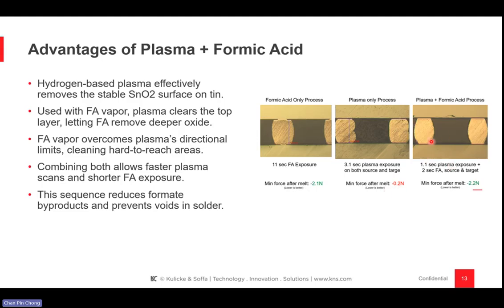And if you look at the combination of both plasma and formic acid process, it reduces from 3.1 seconds to 1.1 seconds for plasma exposure and 2 seconds of formic acid for both source and target, basically creating close to a 3.1-second total exposure time for both plasma and formic acid, and also creates a good force after melt at 2.2 newtons, right? So this is some of the experiments that we are doing, where we have seen the complementary effect of plasma and formic acid in the fluxless bonding process.